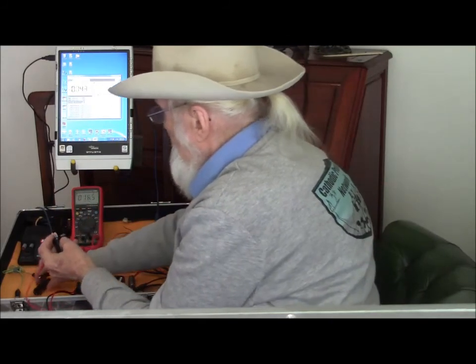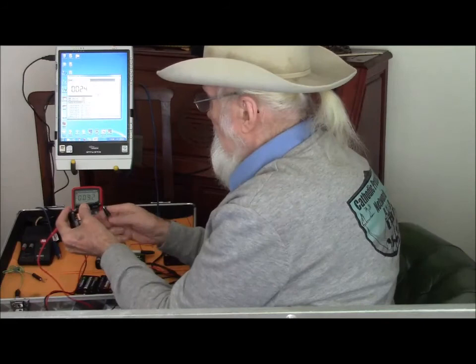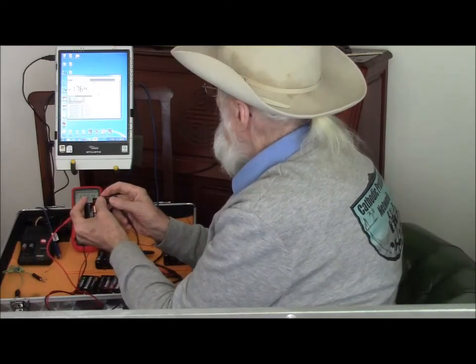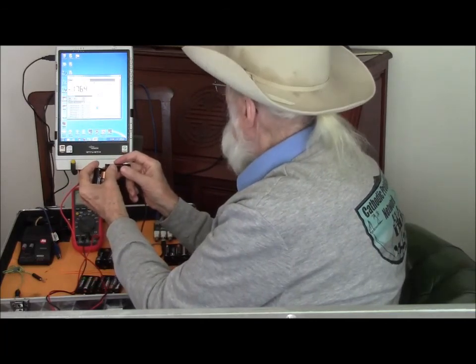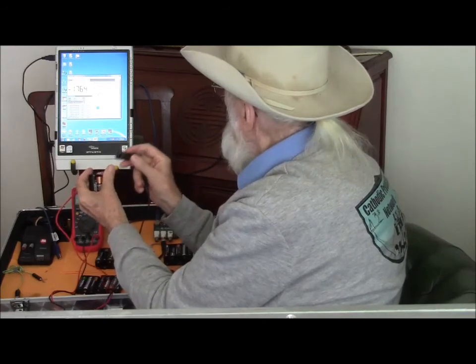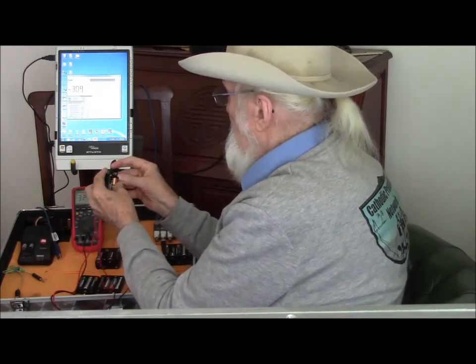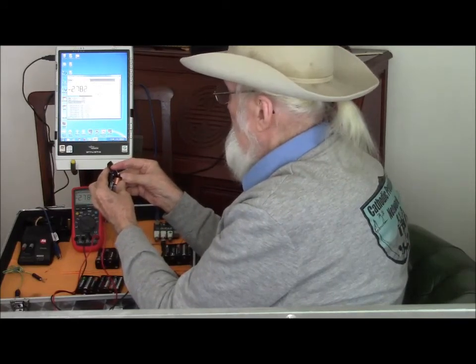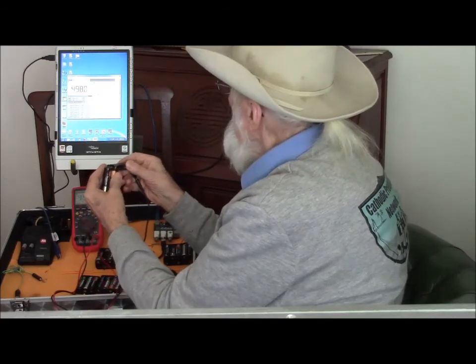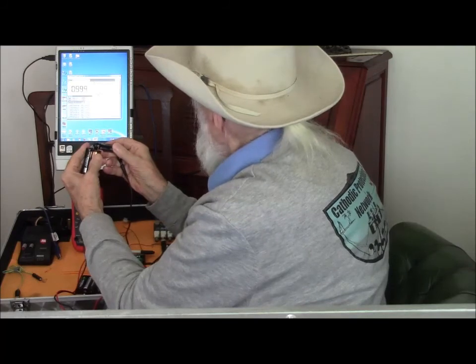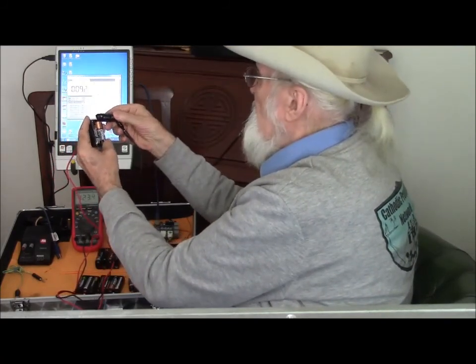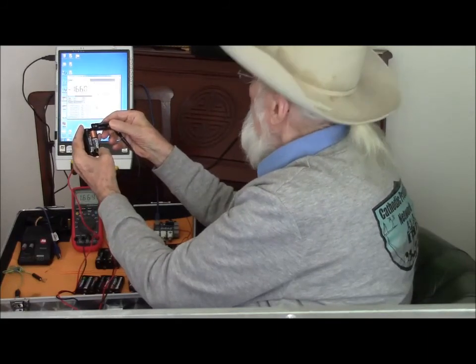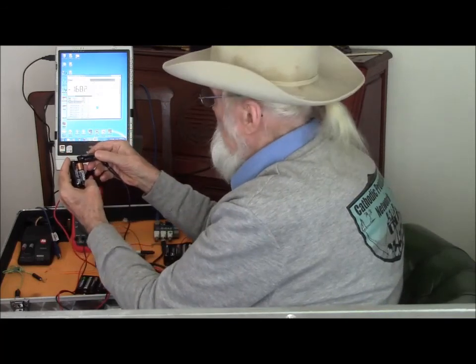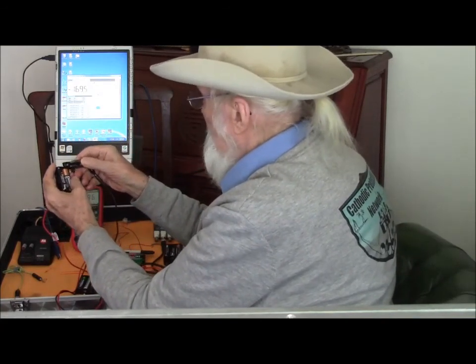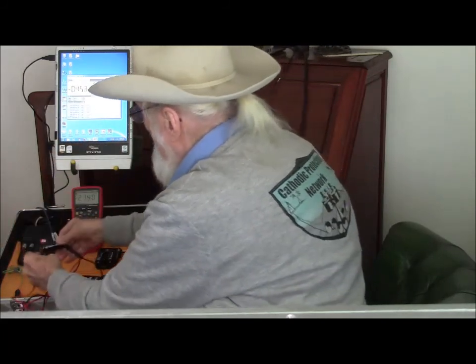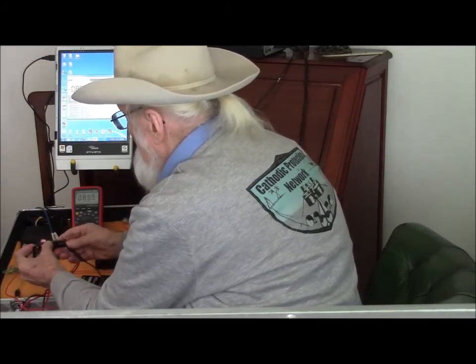It gets worse, because if we add yet another corrosion cell to the recording, we get a different reading. Now, this reading is different from this reading, and it's different from this reading. It all depends how I arrange the corrosion cells that we are measuring. On a pipeline, we cannot arrange the corrosion cells. They are just corrosion cells on a pipeline. And that's the reason why I have made this model,